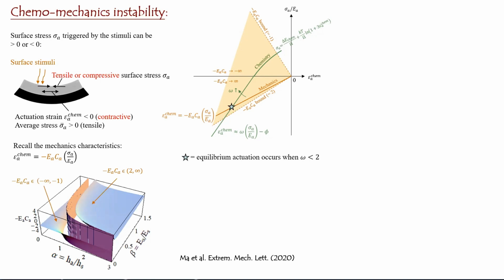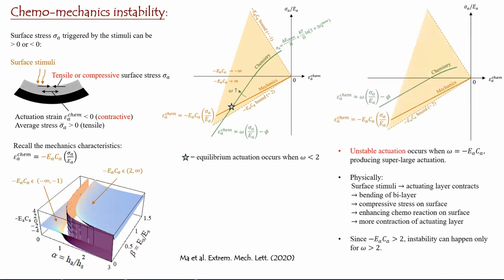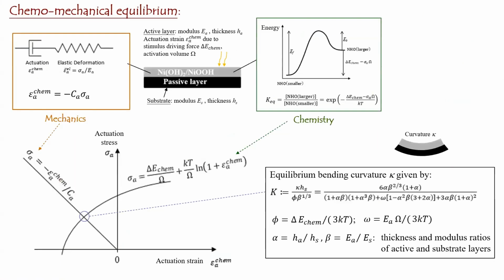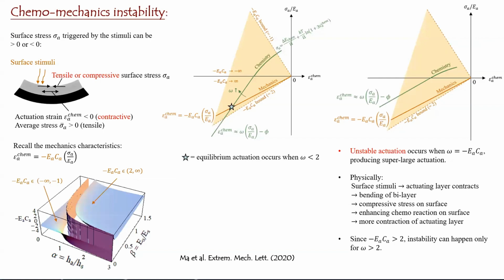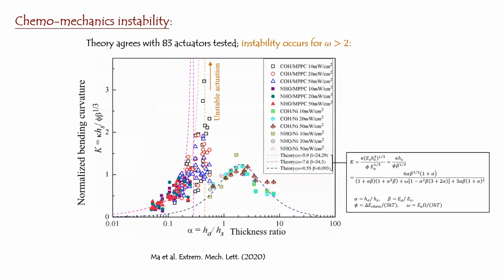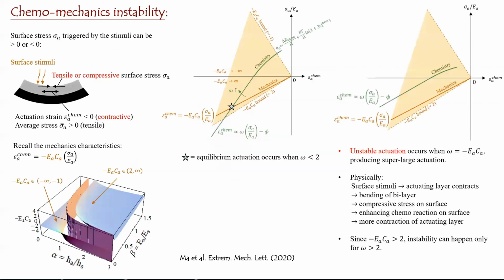So therefore, if you can have that kind of scenario, which is mathematically given by the fact that the chemistry characteristic and the mechanics characteristic become parallel. So there is no intersection. And mathematically, that is given by this condition, then you can have super large actuation. And experimentally, we have also discovered that. Okay, so these few data points correspond to super large actuation. And that happens when you have that magic condition satisfied, which was to have the omega, the normalized activation volume, equals the normalized compliance.